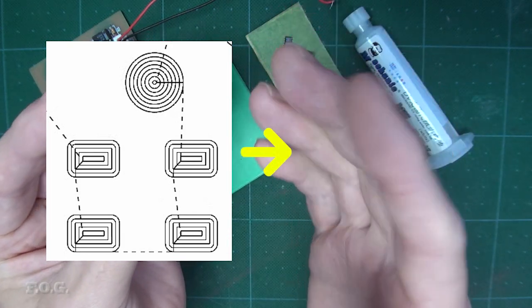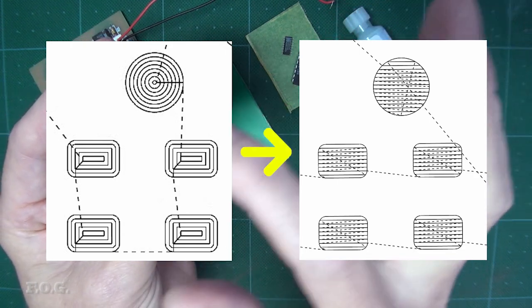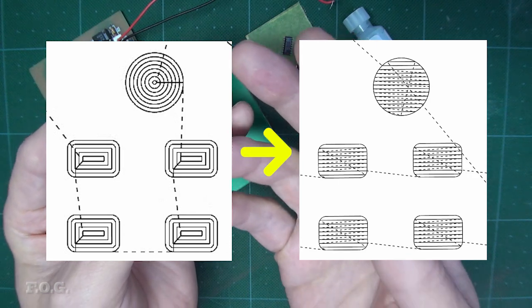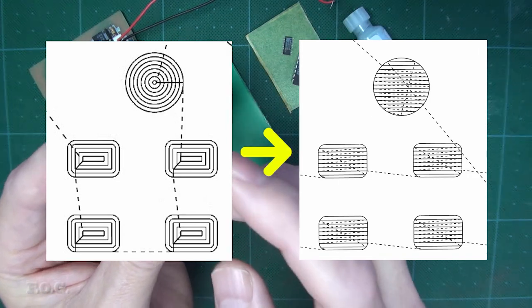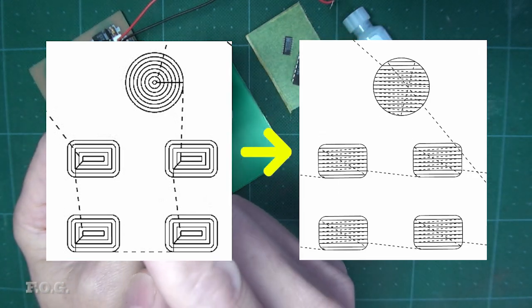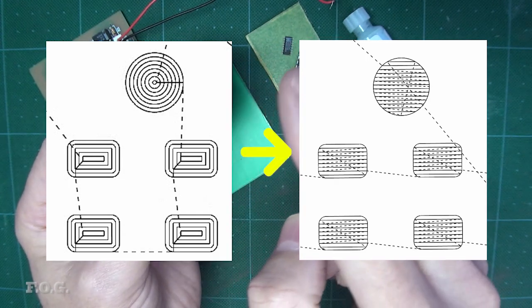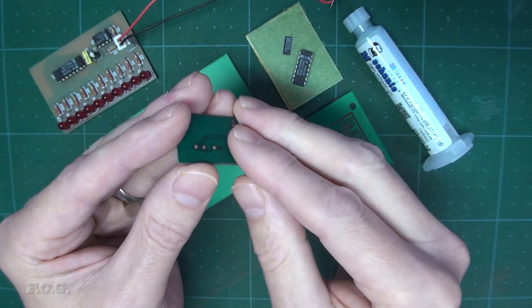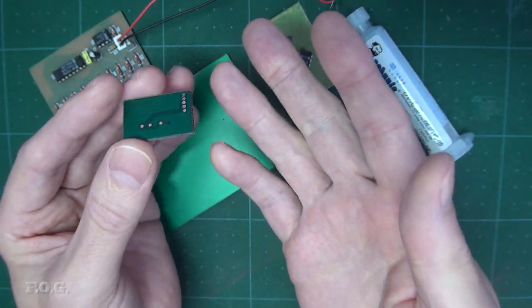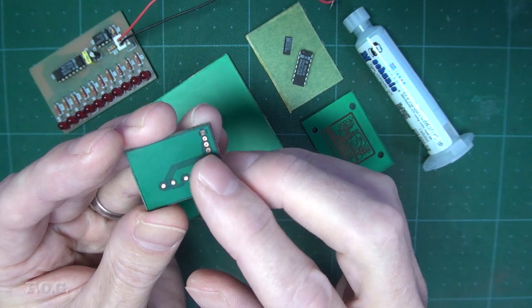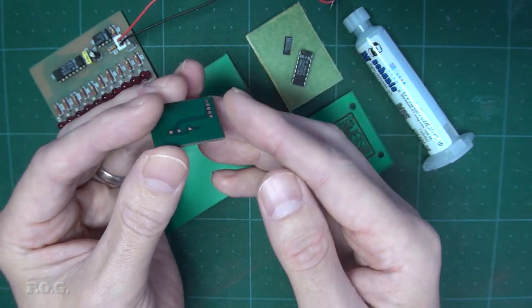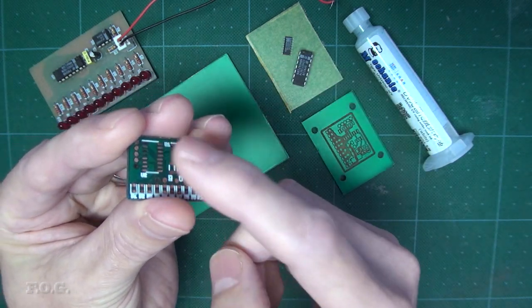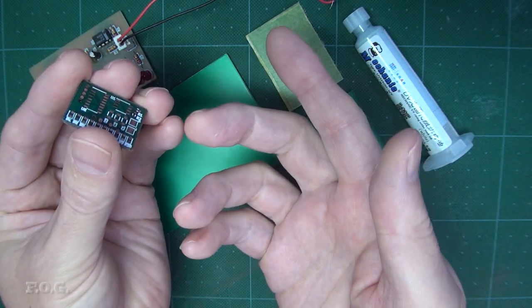For the next try I will clear with a simple outline combined with lines drawn across the entire surface of the pad. I'm thinking that this path will probably stop any focused heat buildup and maybe even allow for better heat dissipation. And as the lines are always burnt in the same direction that creates a little pause before drawing the next line, so that's also going to definitely reduce the pace of heat buildup. As for burning the etch resist layer itself I will also drop the laser power from 50% down to 40%. I'm pretty sure I could probably lower this a little bit more, but as 50% mostly worked fine for this little test board I prefer to play it safe with this setting for now.